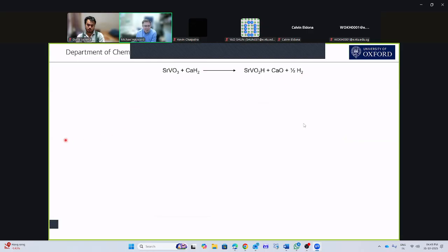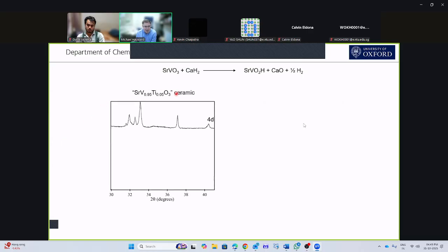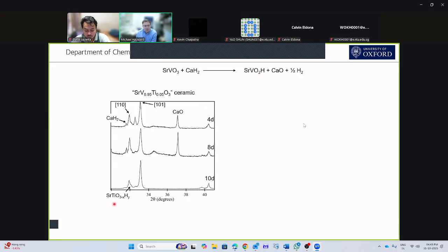and now we're going to take the titanium doped version. So if I take the ceramic version, what I'm showing you here is the X-ray diffraction pattern of this reaction after 4 days. And what we see is we can identify these peaks as calcium hydride and calcium oxide. And then these two peaks, with HKL indices, this is SrVO2H. And then we've got a vanadium titanium oxygen deficient phase. And as we proceed in time, that oxygen deficient phase goes away, and we end up with a single phase of SrVO2H. And if we look really carefully, there's our strontium titanium oxyhydride that came from the strontium titanium oxide that we had in our material.